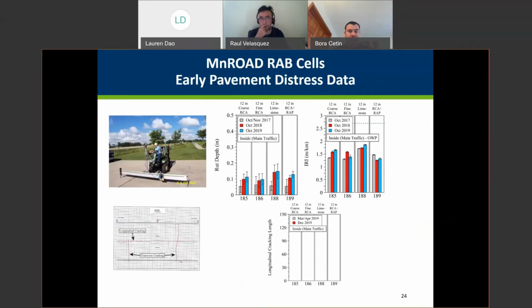So I'm going to show you some early pavement distress data. As Bora mentioned, we collected about 2 to 3 years of performance of these cells. In terms of rutting, in general, all the cells are performing well. Very little distress. In terms of rutting, we have less than 0.2 inches. Very little difference between them. Perhaps RCA cells show a slightly lower rutting. In terms of roughness, they're all below the target limit for the roughness, and they're pretty similar.